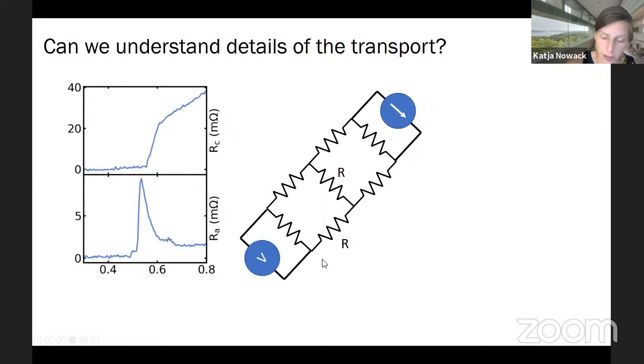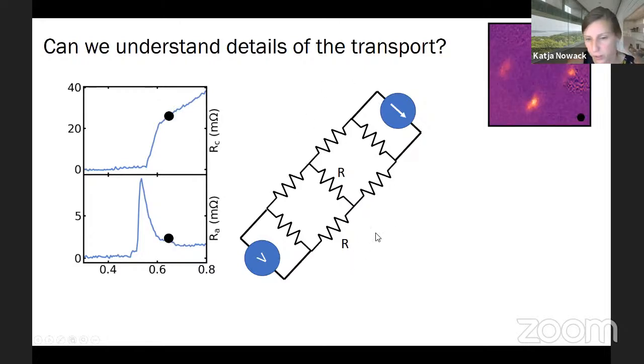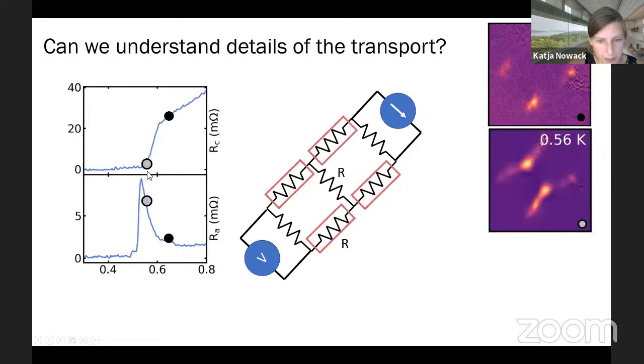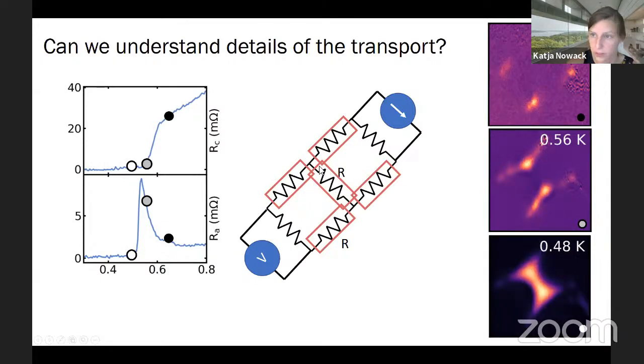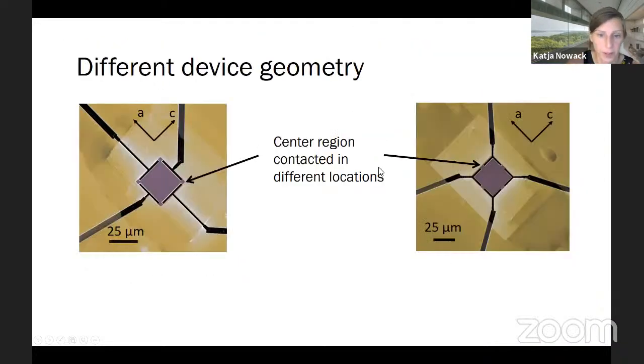That is simply because if I imagine the device replaced by a mini resistor network, at this temperature pretty much all these resistors are still finite. Once I hit this temperature, I should replace these 4 resistors here with a resistance equal to 0. What happens then in the device is that the current that I source between these 2 contacts gets dramatically redistributed across the whole device. Suddenly there's no cost for the current to flow along these sides of the device anymore. And so more current ends up arriving across this resistor close to my voltage probes here, and that causes the spike in voltage, or inferred resistance, at this point in temperature. Okay, and then if I keep going, of course this resistor here will also turn 0 and we measure 0 resistance everywhere. Okay, great.